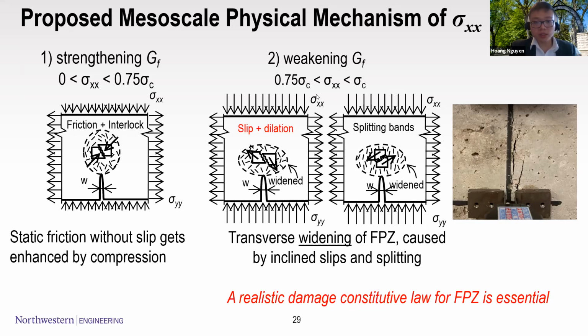However, when you increase the stress closer to the compressive strength of concrete, slip and splitting bands form at the crack tip. Because of this slip and splitting, the material expands in volume at the crack tip, causing a drop in the fracture energy. However, the width of the fracture process zone will be widened. This picture is just eyeballing, and right now we invite collaboration from a group with advanced imaging techniques to prove the hypothesis that we propose here.